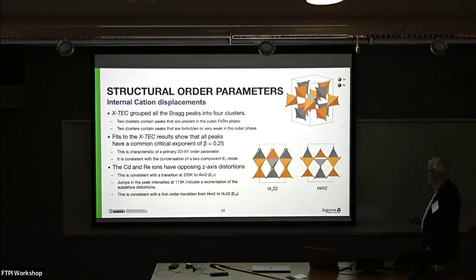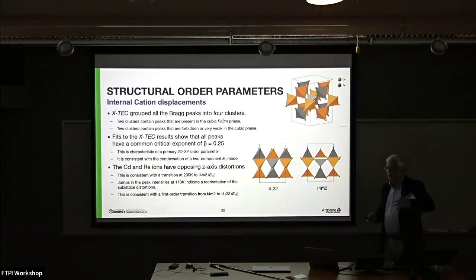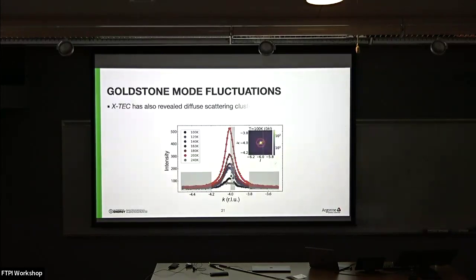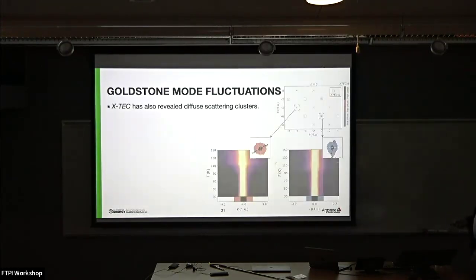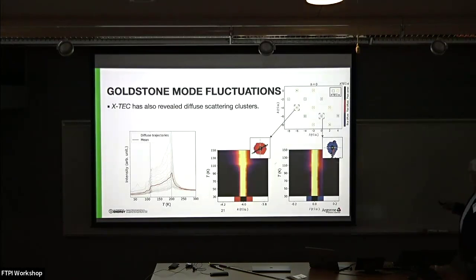Okay, and then as I say, we can even analyze what the distortions are. Interestingly, we're getting the distortions not from fitting the Bragg peak intensity, but from the temperature dependence of the intensity, which is very cool. But there's more than that. If you have something with a Mexican hat potential, you can get very strong fluctuations. You're going to get Goldstone modes within that ring, and indeed we see them. Here is the diffuse scattering around the Bragg peaks, and XTEC can cluster diffuse scattering as well as the Bragg peaks. If you do that, we see that the same sets of two peaks that I showed before have distinct diffuse scattering around them, with distinct temperature dependencies, and you can cluster them as well.